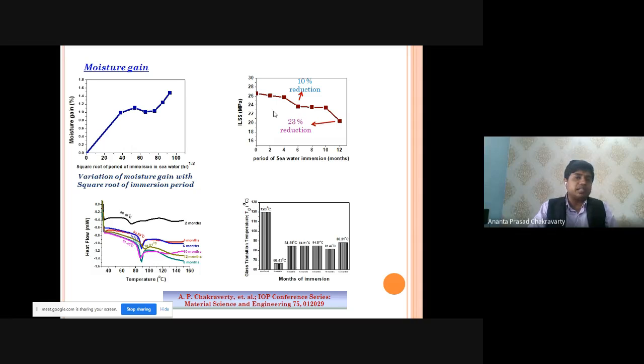Similarly, its interlaminar shear strength also decreases by up to 23% after 1 year. That means I have to keep in mind its design stress, so that I can account for that 23%, so that the material can be used in seawater with sustainable performance. And I have studied the glass transition temperature by differential scanning calorimetry. After 1 year, that temperature is 88.21 degrees centigrade, from 120 degrees centigrade. That means up to 80 degrees centigrade the material can sustain in the sea. Okay, I can use it up to 1 year.